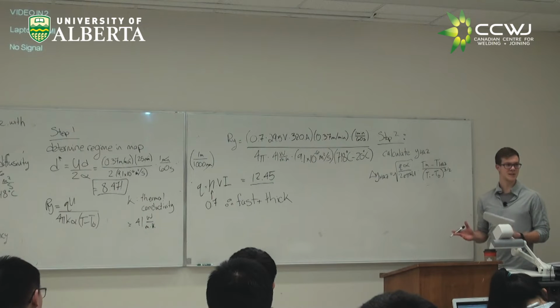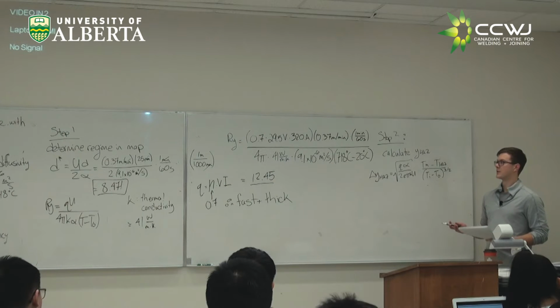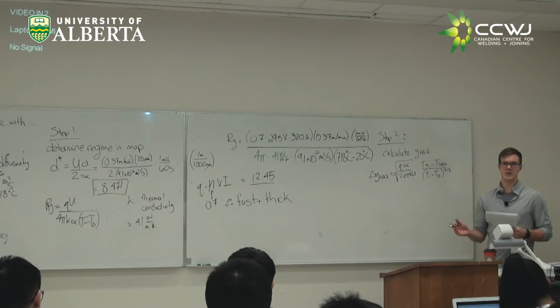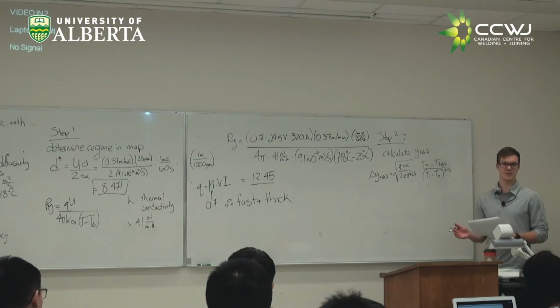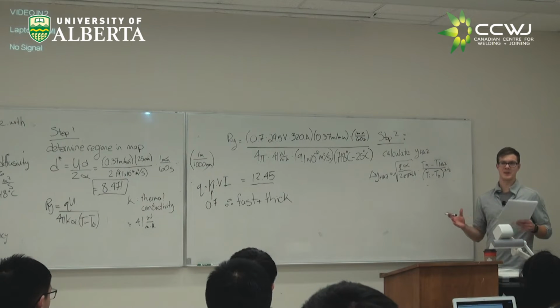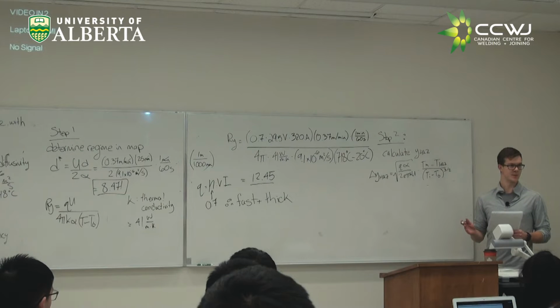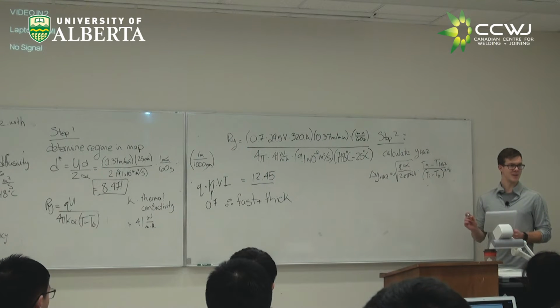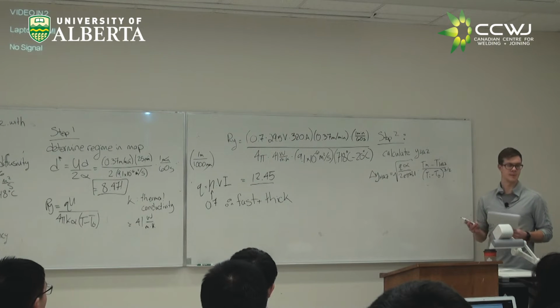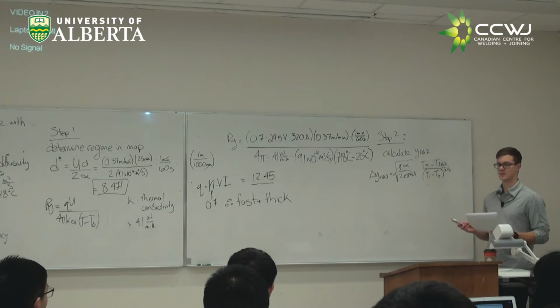Typically an intermediate temperature works, but you'll see from the process map, if we change our temperature from 718 to 1045, typically that's not going to be a big enough change to put us in a different regime. If you're right on the boundary, then maybe you want to double check that you're using exactly the right kind of moderate temperature. But typically that's not a big concern.